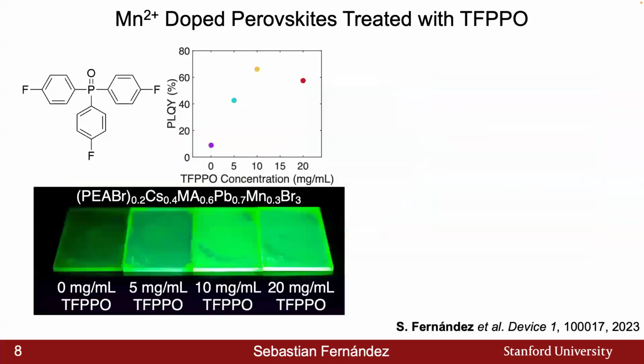And so that brings us to the first story today, in which we look at pairing a phosphine oxide additive with the manganese-doped perovskite LED platform. Here I'm showing trifluorophenyl phosphine oxide, TFPPO, and we're able to introduce this to the perovskite material via the chloroform anti-solvent. We focus on concentrations of 0, 5, 10, and 20 milligrams of TFPPO per milliliter of chloroform anti-solvent that is solution processed within this thin film.